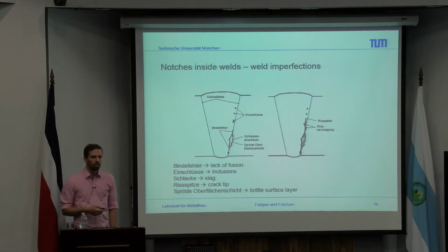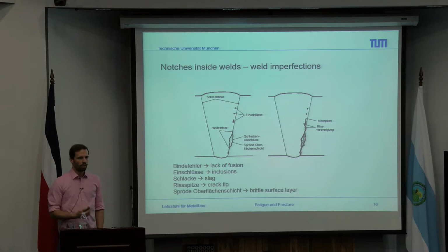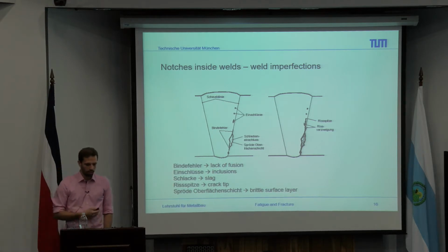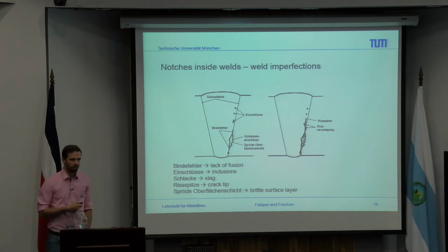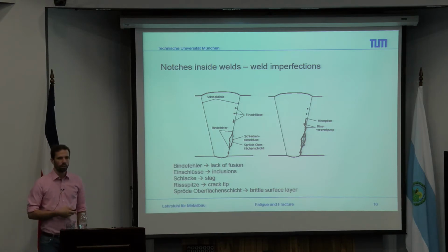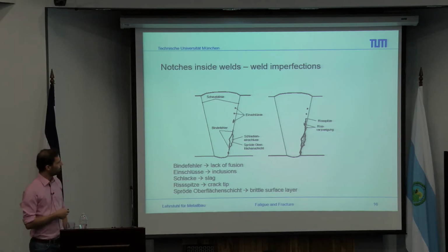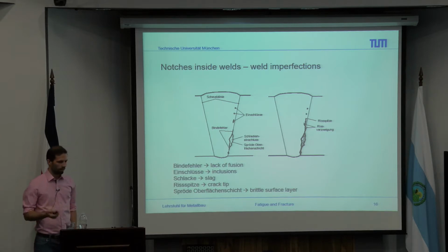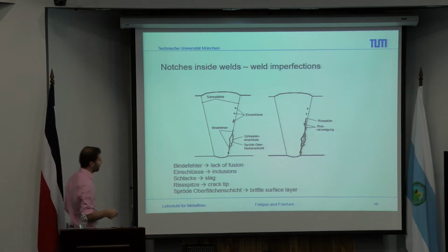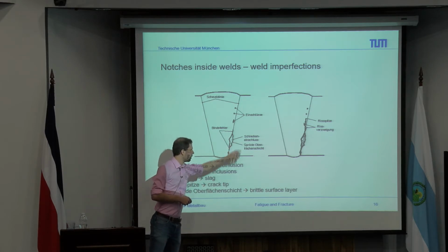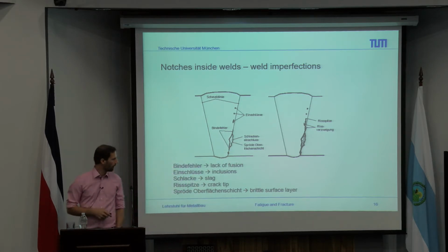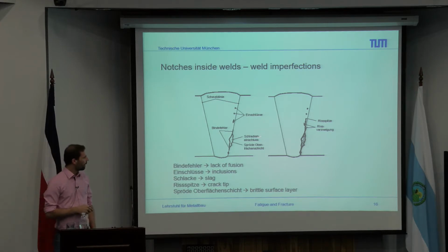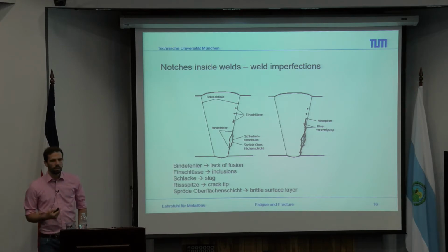And the inclusions are some material which is in a really bad condition, which may occur due to the welding process, due to some bad welding parts. The next one are also the slags, which can also appear next to the lack of fusion, and also some brittle surface layer. This brittle surface layer can occur at this part, and also in this part.